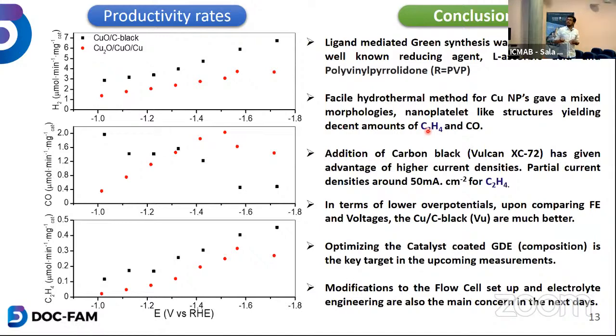When I talk in terms of partial current densities, we are reaching 50 milliamps per centimeter square for ethylene. I think it's not up to the mark compared to 150, which is published in a couple of papers, but it's quite a good amount. And of course, I'm working to enhance it to at least 100 or 200 milliamps per centimeter square.